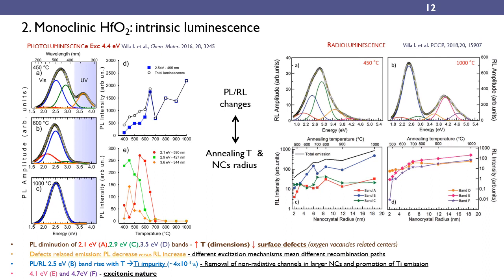Photoluminescence and radioluminescence change as a function of the temperature. By looking at the photoluminescence under UV excitation, 4.4 electron volt or 280 nanometers, we notice that while the annealing temperature is increasing, the shape and the intensity of the photoluminescence are changing. At low temperature, nanocrystals show a spectrum composed by 4 bands at 2.1, 2.5, 2.9 and 3.5 electron volt. At high temperature, the dominant band is the one in the blue range at 2.5 electron volt, while all the other bands disappear.